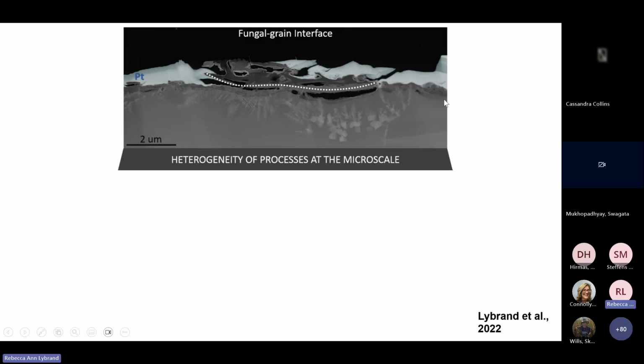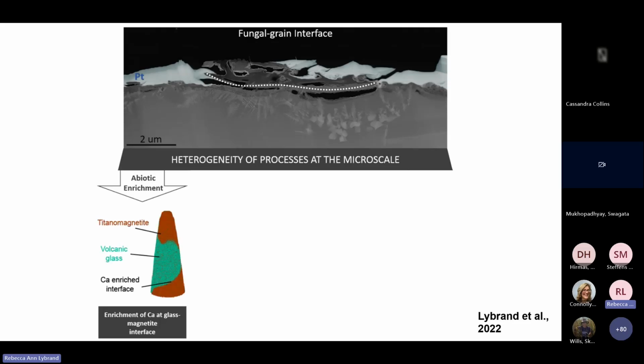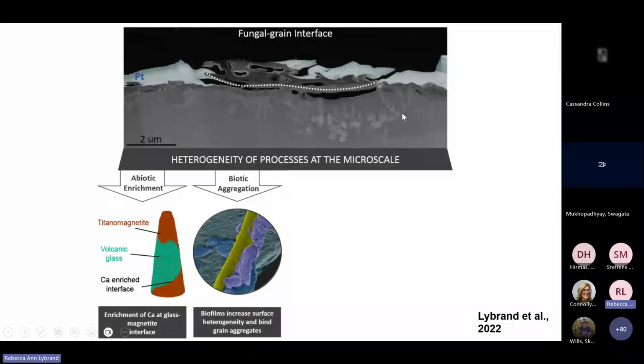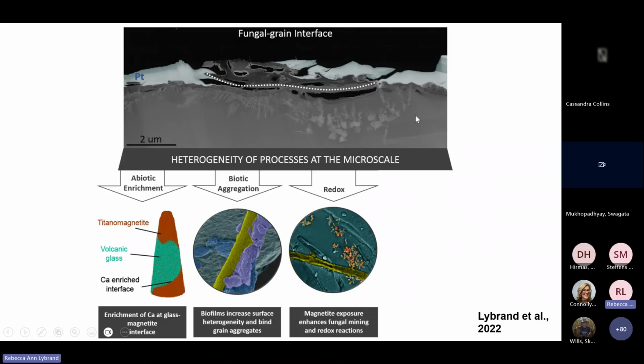And through this collaboration with PNNL, we were able to use several different technologies at the same interface, where we could look at this direct contact between the fungal grain interface, and also understand abiotic enrichment going on between the magnetite and the volcanic glass matrix that you see here, using atom probe tomography, or APT. We were also able to think more about biotic aggregation and the influence that biota are having at this particular interface. And then even thinking about the fact that interactions like this are exposing these underlying inclusions of magnetite. So there could be fungal mining or fungal interactions going on, and then it exposes magnetite, which could lead to subsequent redox reactions, as one type of example.